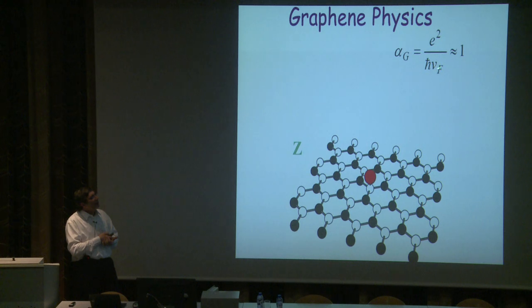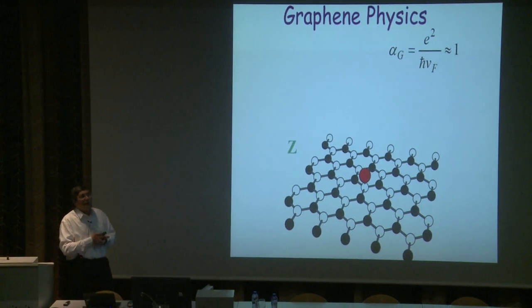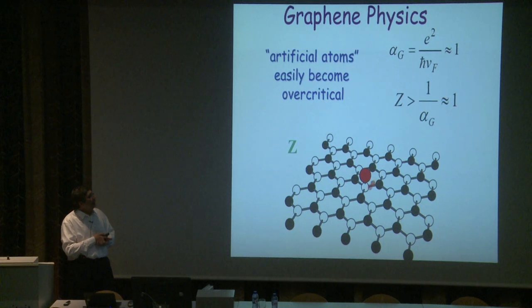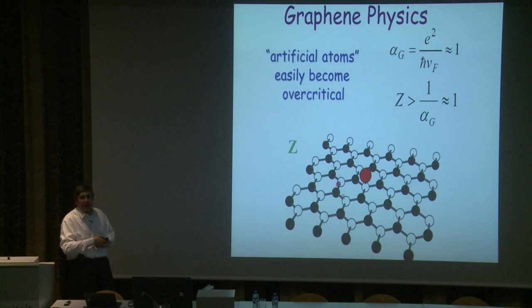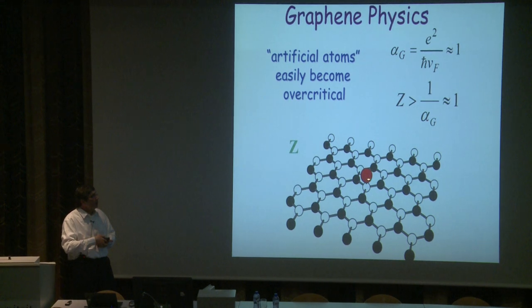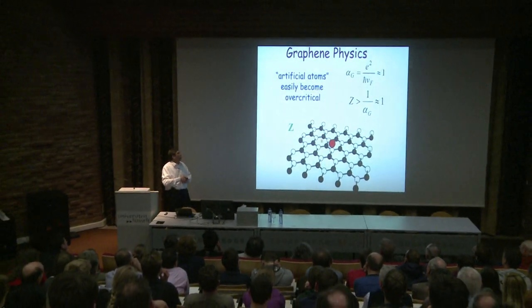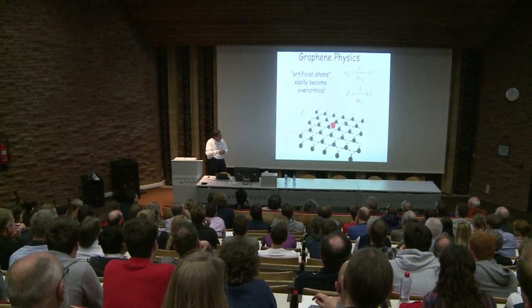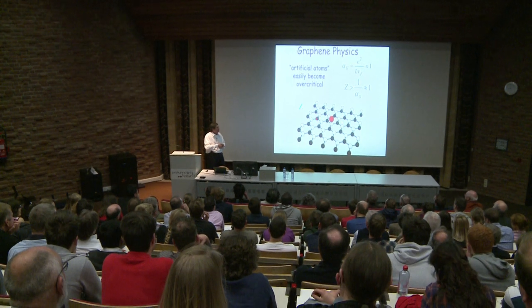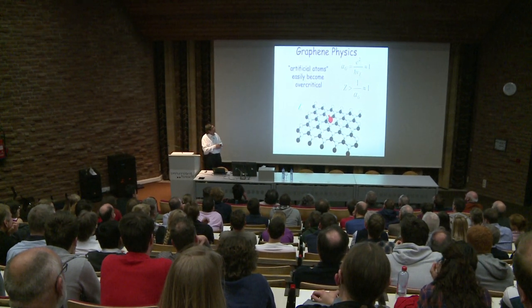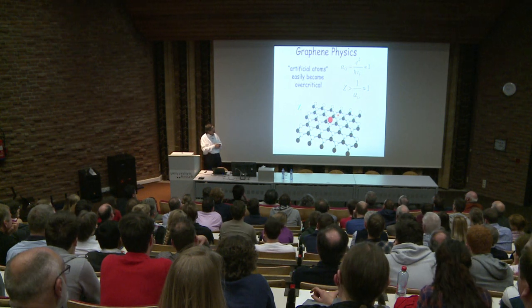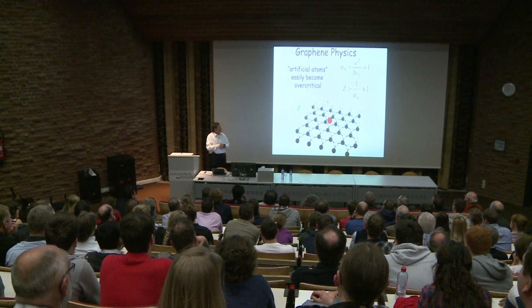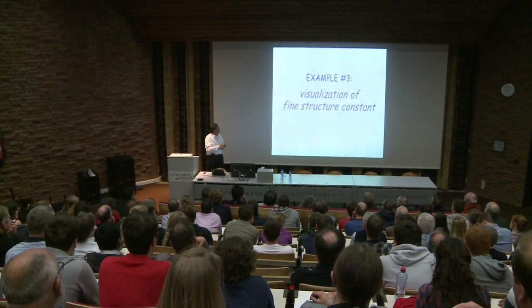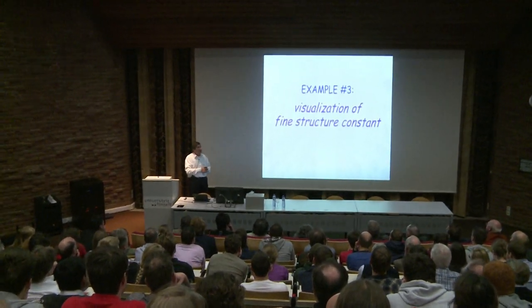So this number is 300 times smaller. So the interaction between electrons and charges in graphene is very strong, it's about one. So in this case, even if you put one charge, actually people did this experiment only this year, they managed to succeed in doing this experiment in graphene. They put four calcium atoms together and they have seen this phenomenon: negative charge goes in, positive charge is injected. It's seen like some weird screening. But this phenomenon at last has been proved thanks to graphene, so we can confirm that those theories were all right.